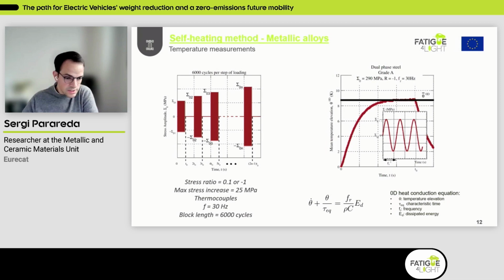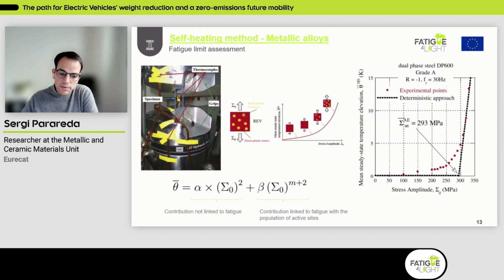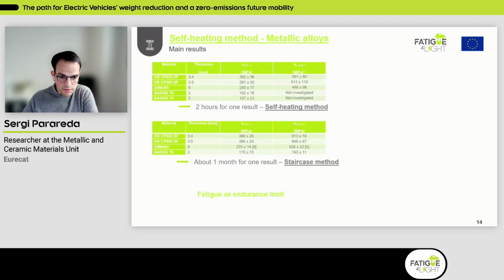So here we are also increasing the stress amplitude between each one of these fatigue blocks. And by having this evolution of temperature plotted against the stress amplitude of each one of these fatigue blocks, these are the results that you can see here on the right-hand side, then we can obtain the fatigue limit of the material also in a very easy way. And in this case, we only need these different thermocouples attached to the grips and also to the specimen to evaluate the temperature evolution in the material.